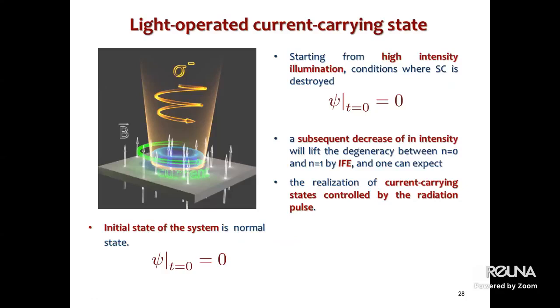So as indicated, the two states, n equal to 0 and n equal to 1, are degenerate, separated by a free energy barrier. Starting from high intensity illumination, we start from the normal metallic state. Superconductivity is destroyed, and then we subsequently decrease the light intensity. The presence of light will lift the degeneracy by the inverse Faraday effect, and one can expect a realization of current carrying states controlled by a radiation pulse. This is the original expectation.